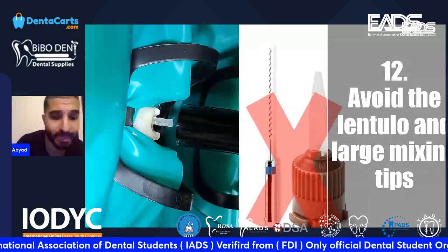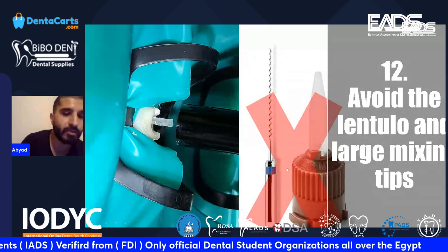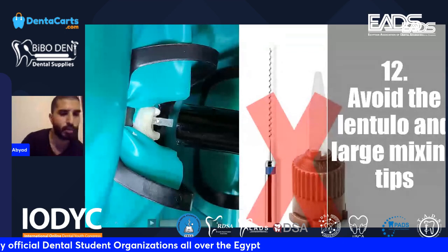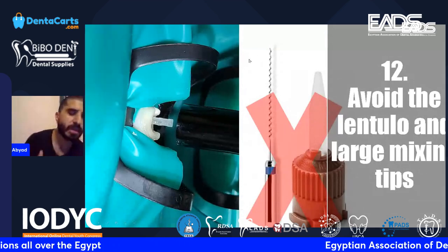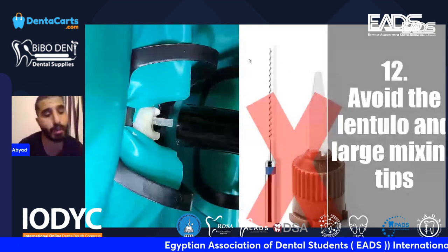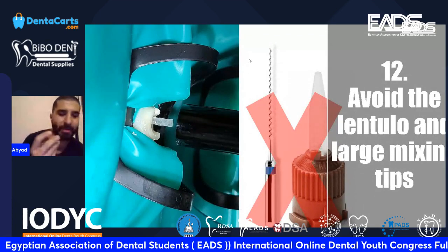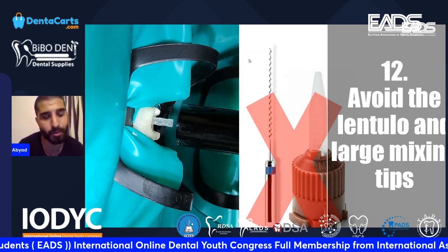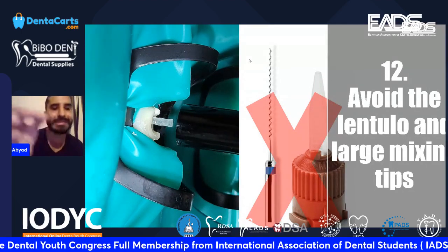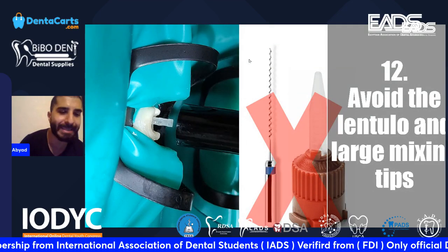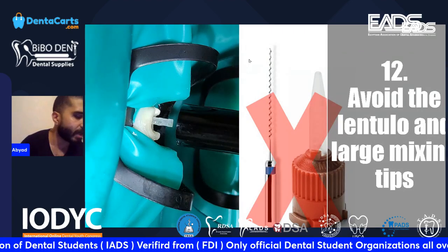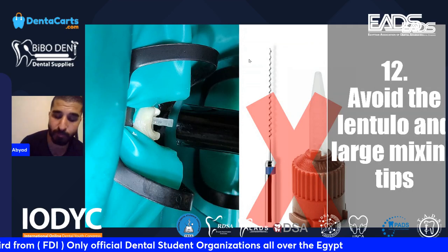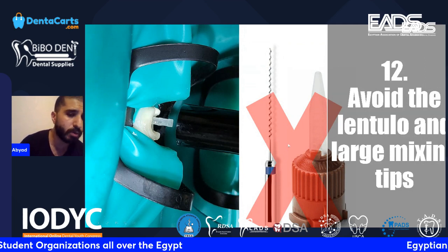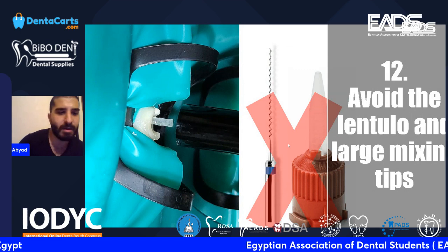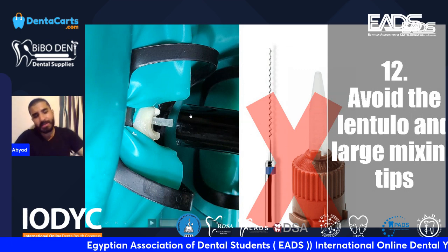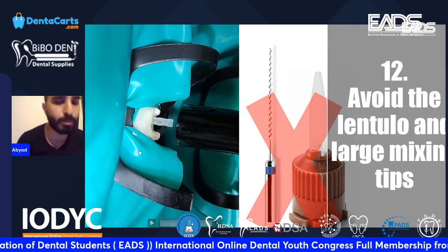And if you are using a resin cement, and I've had personal bad experience with the lentulo spiral, just try to avoid this one. Just get the small injection tips, and you will be good. The lentulo spiral could cause heat generation inside of the cement, and it would cause premature setting of your cement. Your cement could turn into a crumbly type of solid, and it could block your space. So imagine injecting a cement inside of the post space, then placing the post, and then suddenly it does not want to get inside. I think you would get a mini heart attack if that happens. For this reason, just avoid anything that could generate heat inside of the post space. Just get the small tip, inject your resin cement in a stress-free environment. That's another reason why I say place a rubber dam, because you want this whole procedure to be stress-free.